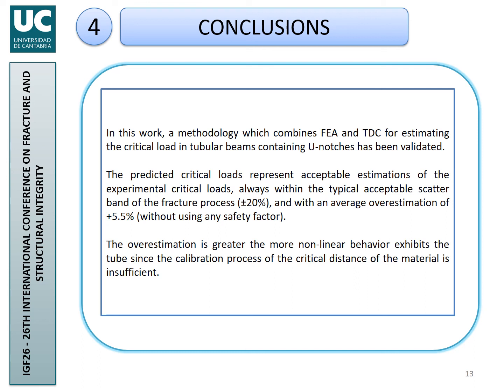The predictions fit quite well the experimental results, all of them being within the acceptance margins and with an average overestimation of 5% approximately.